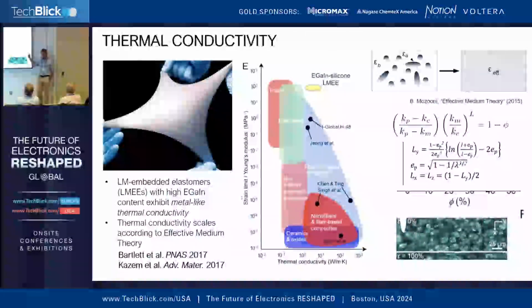So just very quickly, I want to mention one feature of these composites: if we have a high concentration of droplets and they're not touching each other, we get rubbers that are electrically insulating but thermally conductive. And we actually approach metal-like thermal conductivity. This didn't render properly. Sorry for this. I'll just skip ahead to this next slide, which highlights some of the work we're doing.